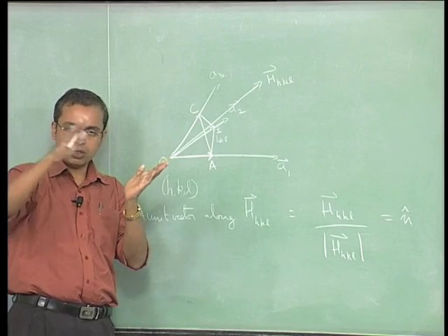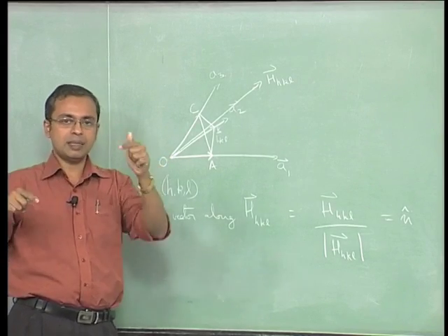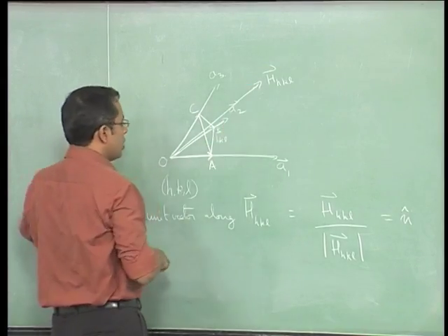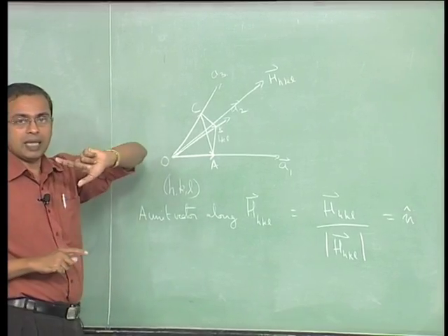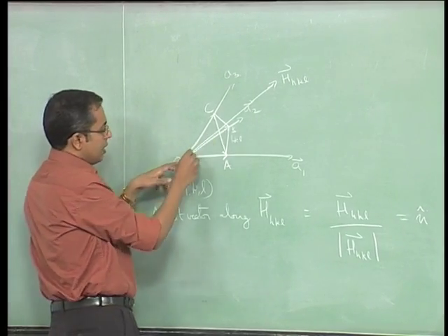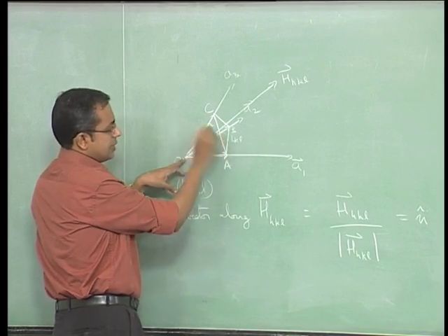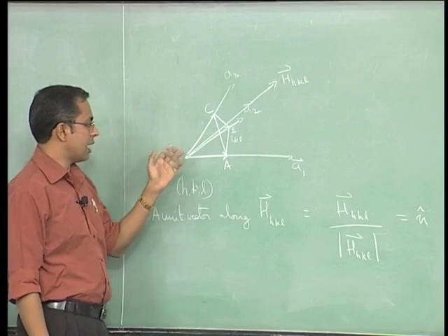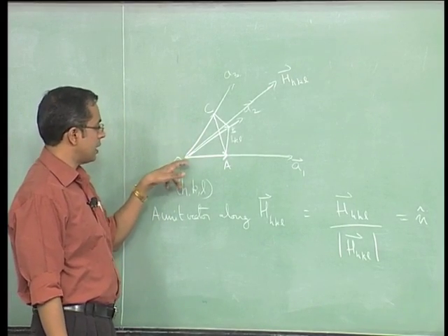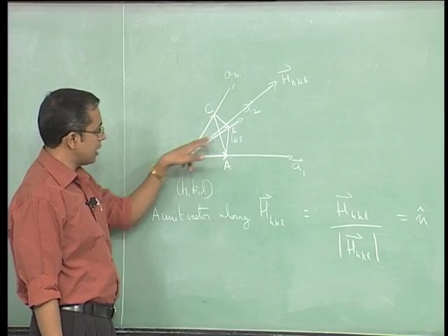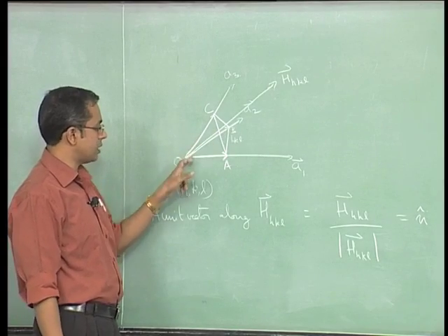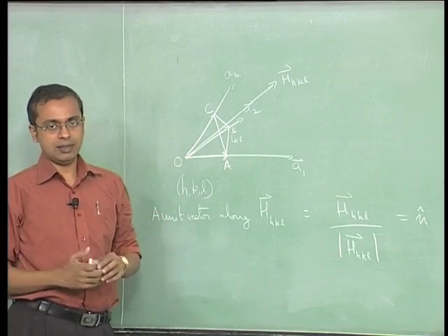We take the one closest to the origin and take its intercepts, and that is how we come up with HKL. So the spacing between the HKL planes is simply the distance between the origin and this HKL plane, the closest distance, which is therefore dHKL.